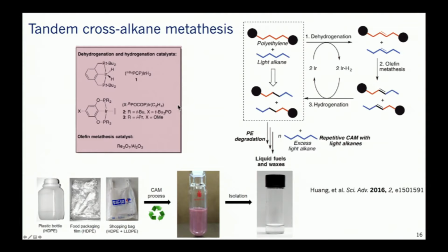And then cross metathesis using a second catalyst, in this case a rhenium-based catalyst, will swap the chain ends and basically cut the chain in the middle. And that would be a very endothermic process, except that you've generated hydrogen in that process, and when you rehydrogenate the polymers, you get back to your alkanes. And so the entire process is nearly thermoneutral. Overall, then, you can use this kind of a dual process to take polyolefins down to low molecular